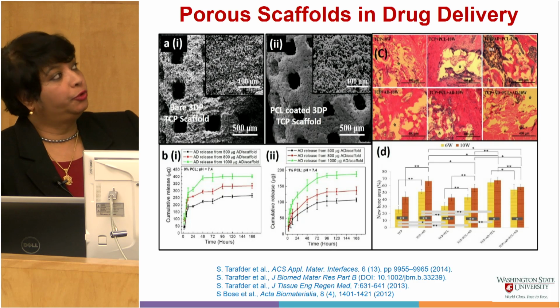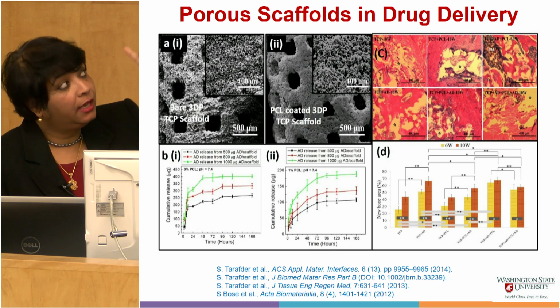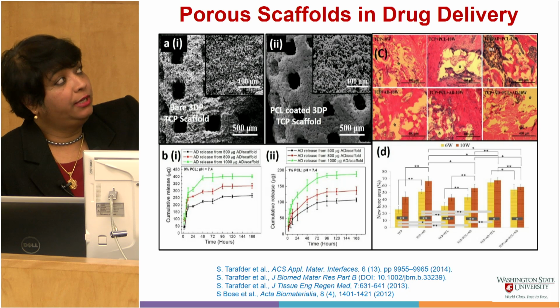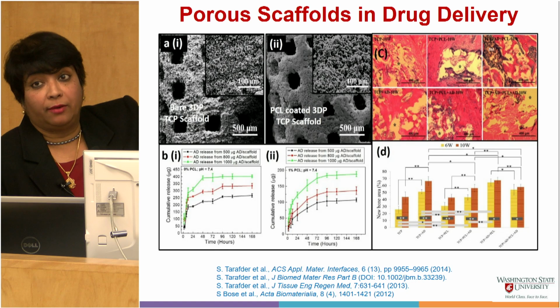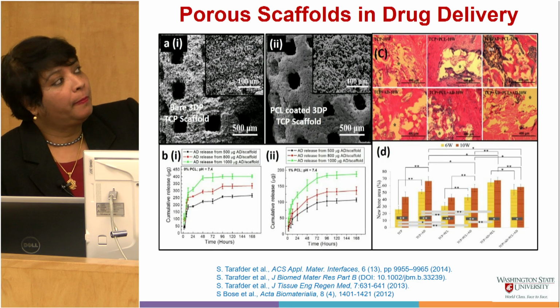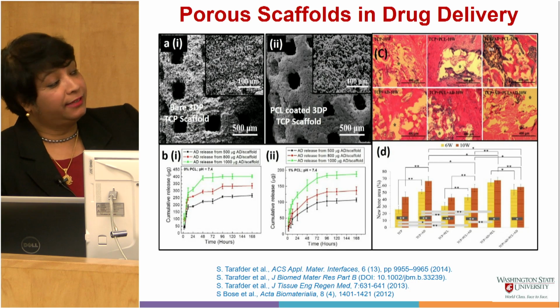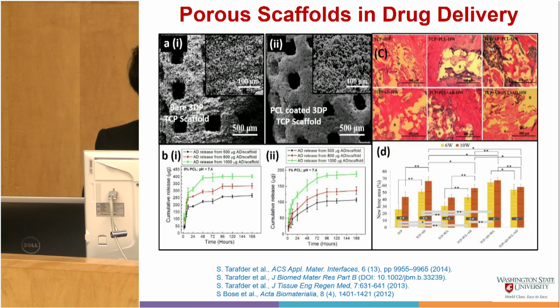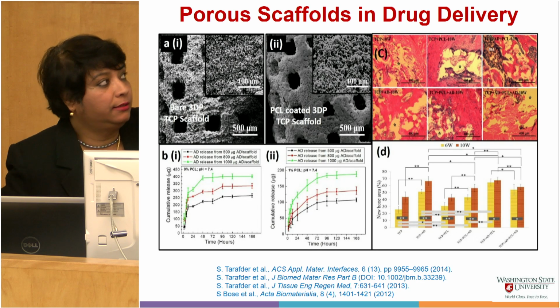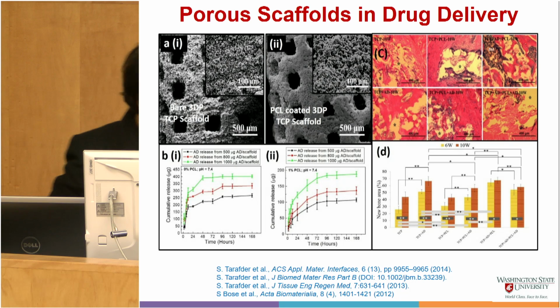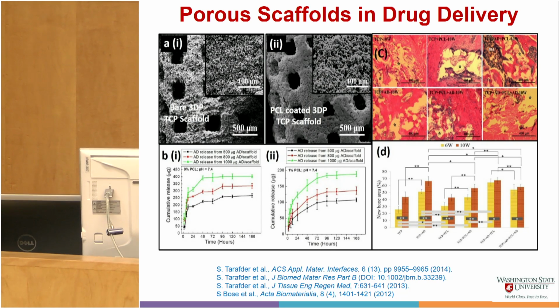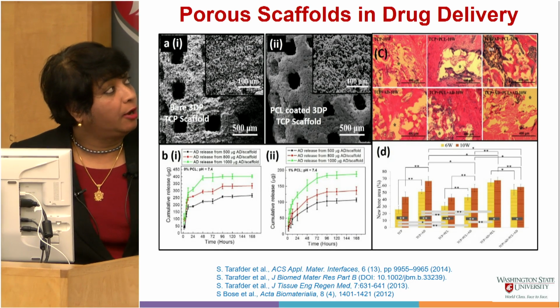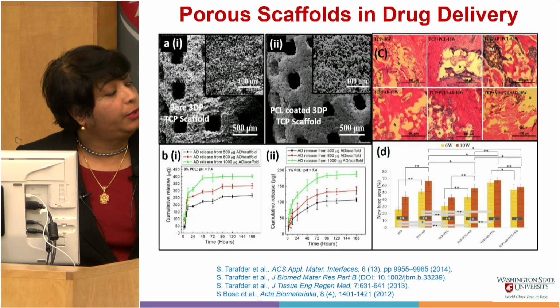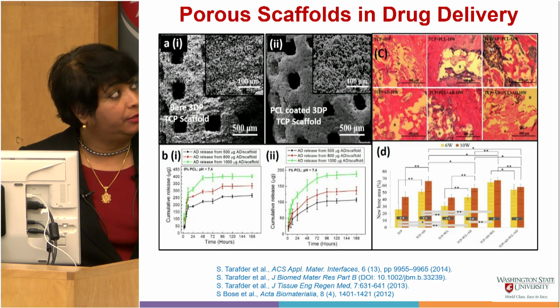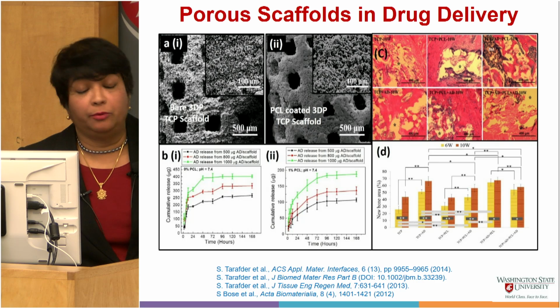It tends to show very fast release kinetics. On the top right, the red one you are seeing, those are all newly grown bone in porous scaffold in rat distal femur model. And the bottom plot, I know it is crowded, all it is showing is, wherever this red and the yellow bars show different compositions, wherever we had alendronate in the composition, it showed higher bone area.